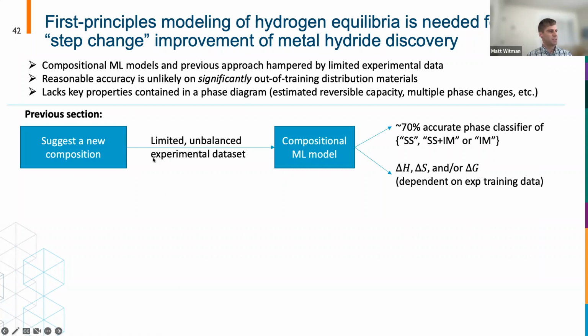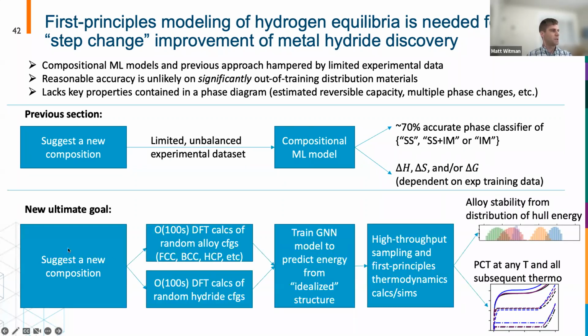We want to know what happens if there are multiple phase changes, et cetera. So before, we would just suggest a new composition, and based on our limited and unbalanced experimental training set, we would train a model and filter things based on a simple phase classifier and try to directly predict these properties. But our new ultimate goal is to suggest a new composition and actually do DFT screening of random alloy configurations and random hydride configurations in these exemplar lattices, and use graph neural network models to predict the formation enthalpies in high throughput from an idealized structure representation, which I'll mention in a minute. And if we can do that in high throughput, then we can feed first principles thermodynamics calculations or simulations to more rigorously predict the alloy stability itself, and then finally directly predict the pressure-composition-temperature curves and subsequent thermodynamic properties.